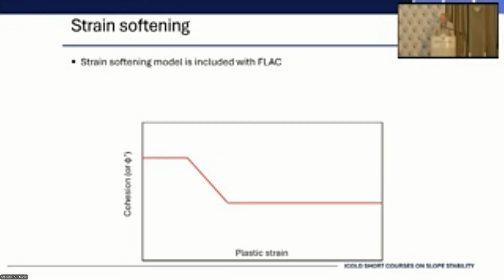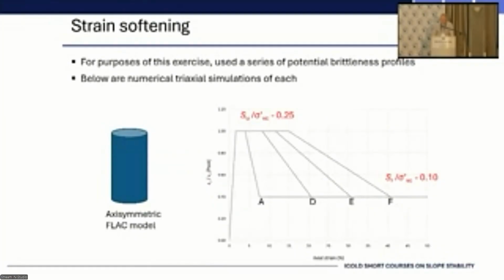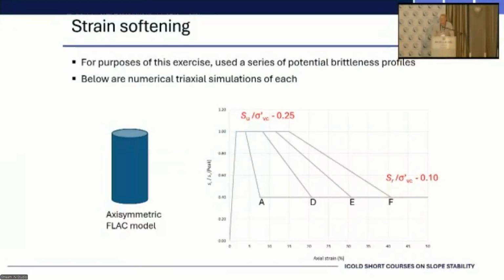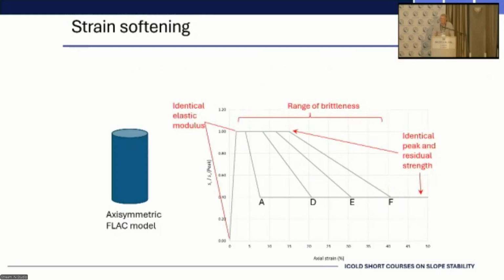Now, this is not meant to indicate this is realistic behavior. This is indicative behavior of strain softening. So keep that in mind. But if you look at different versions of that strain softening, so same peak undrained shear strength, Su over sigma'v of 0.25, and same post-peak, 0.1, but different strains to mobilize that large strain. So what do we get?